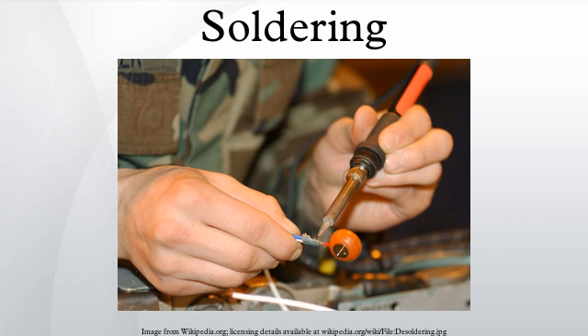Electronics. Various problems may arise in the soldering process which lead to joints which are non-functional either immediately or after a period of use. The most common defect when hand soldering results from the parts being joined not exceeding the solder's liquidus temperature, resulting in a cold solder joint. This is usually the result of the soldering iron being used to heat the solder directly, rather than the parts themselves. Properly done, the iron heats the parts to be connected, which in turn melt the solder, guaranteeing adequate heat in the joint parts for thorough wetting.